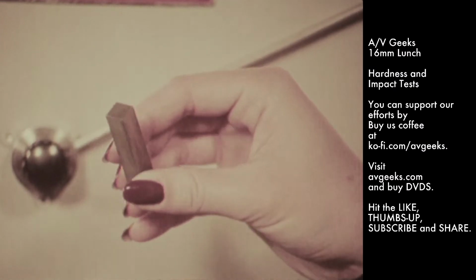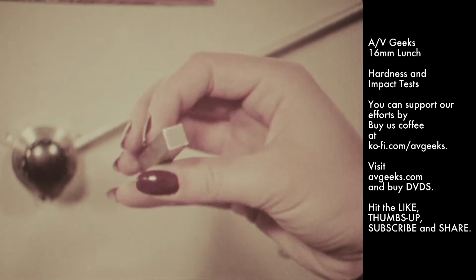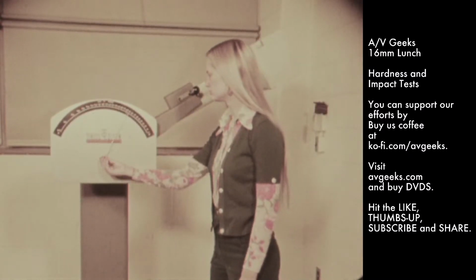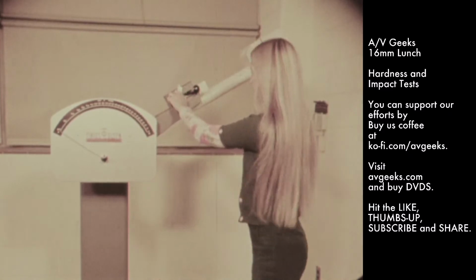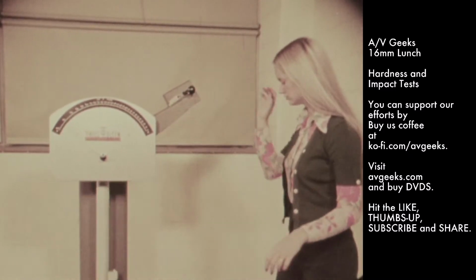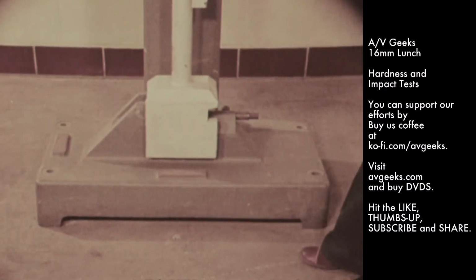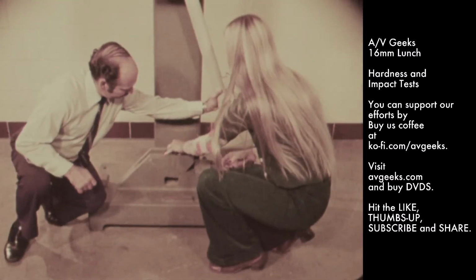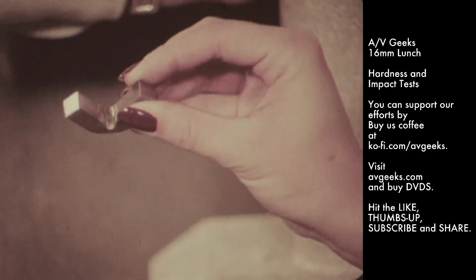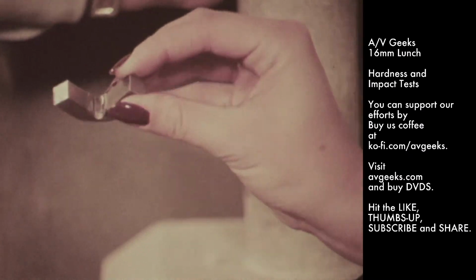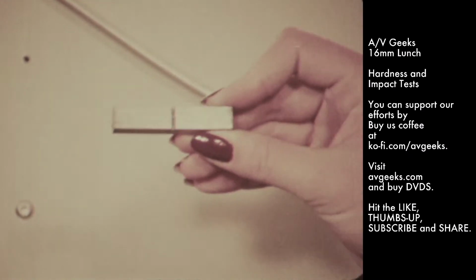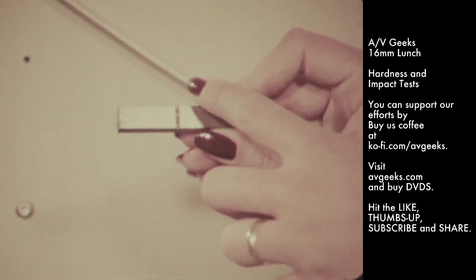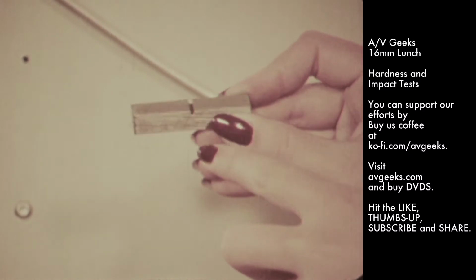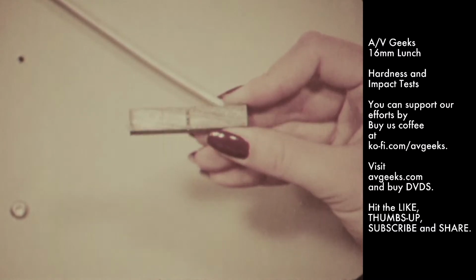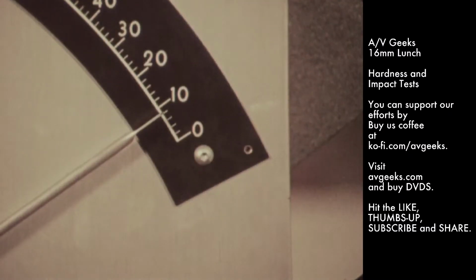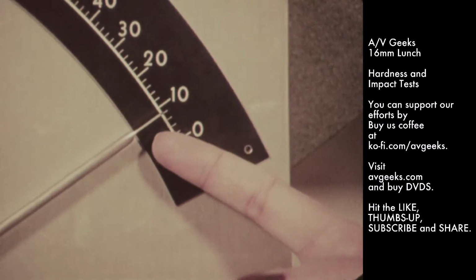Some materials, such as this SAE 4140 steel, do not break under a single impact. In an impact test, the total energy absorbed to fracture is desired. But this specimen did not break. Specimens are therefore notched. In addition to producing a stress raiser, the notch concentrates the energy at a narrow region. A notched 4140 specimen does break.